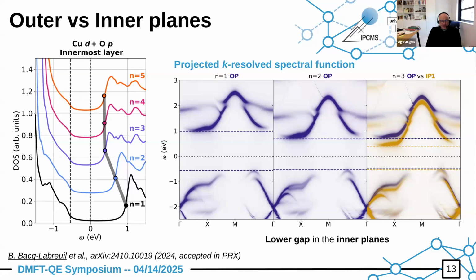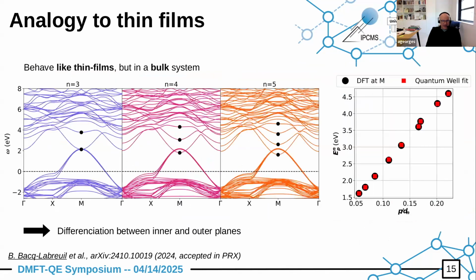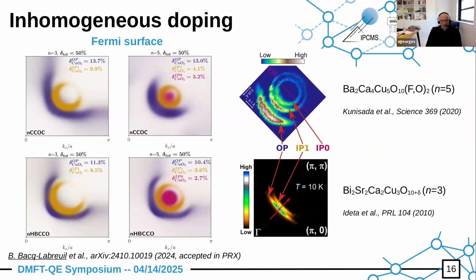Can you show again your Fermi surfaces for the different layers? Thank you. So I want to make sure I understand that. What you are saying is that the inner layer has a very low doping level, right? And then it leads to a very small pocket, which seems from the plots to be centered around the nodal point, around (pi/2, pi/2), correct? Exactly. And how does that happen? Is this because of the antiferromagnetism? Is the calculation, in fact, in an antiferromagnetic state, or what's going on here?